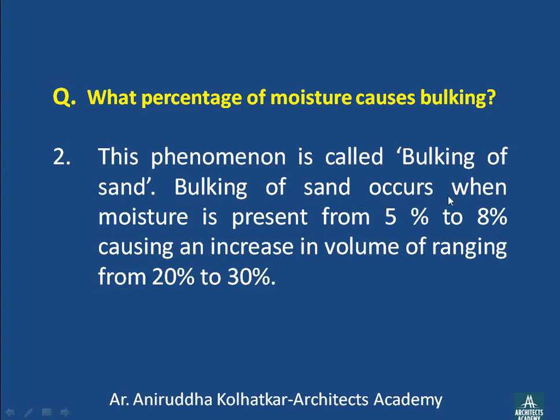Bulking of sand occurs when moisture is present from 5 to 8 percent, causing an increase in volume ranging from 20 to 30 percent. This bulking occurs in a very small range of 5 to 8 percent, and in that case the increase in volume is quite a phenomenal increase - between 20 to 30 percent.